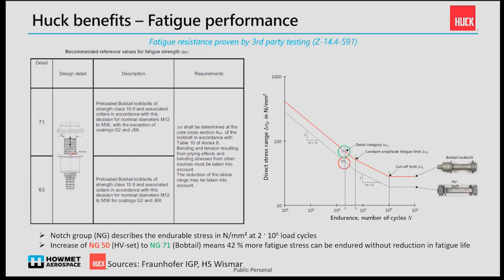So just to get an impression, the fatigue resistance of a threaded fastener is usually not more than 10% of the static load capacity, mostly even less. And due to our special thread design, we have at least 3 times the fatigue resistance of a conventional threaded fastener. This has been tested in a big test program.